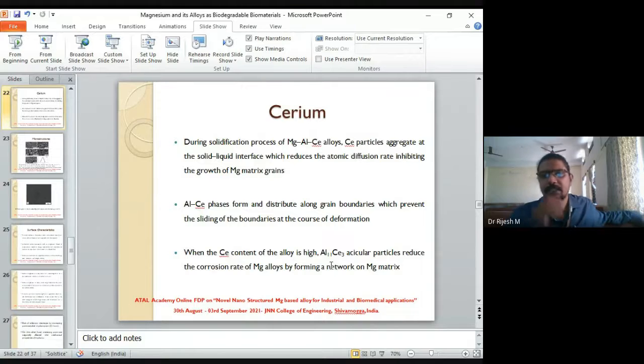Cerium is another metal that we add to improve the corrosion resistance. During the solidification process of magnesium aluminum cerium alloy, cerium particles aggregate at the solid liquid interface, which reduces the atomic diffusion rate, inhibiting the growth of magnesium matrix grains. Again, this cerium is also a grain refiner, just like strontium.